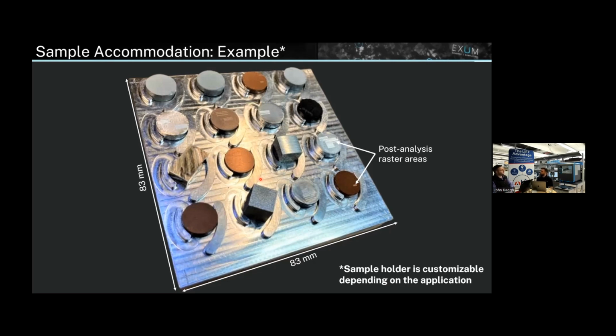And then what about pump down time? So you have the chamber open, you put your samples in, you press close, and then how long until we're ready to go? All the lights are green and then the laser starts firing. Yeah, so about 10 minutes till you're doing your first analysis. After that 10 minutes, what we'll generally do is our first cleaning run. Somebody asked about contamination on the surface. We'll do a first pass. We'll say, hey, what's the surface looking like? Maybe we want to clean it off. And then for the quantitative runs, we wait about another 5 to 10 minutes or so, or while it's being analyzed, we go back, put our quantitative runs in, and we're up and running.